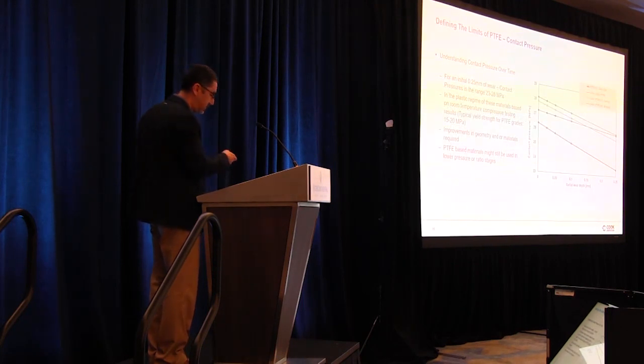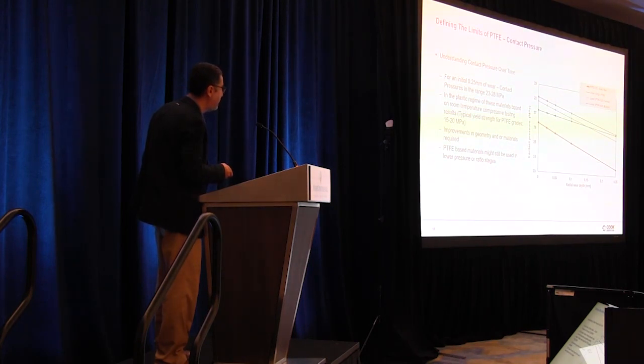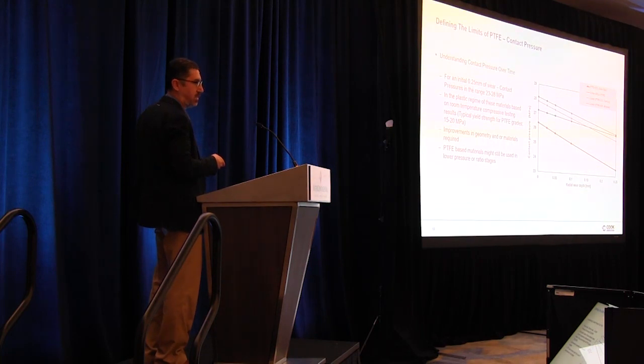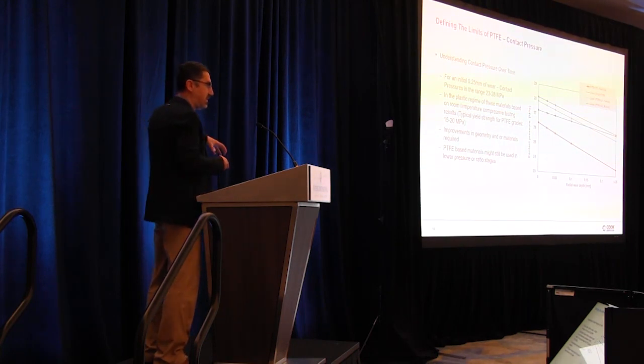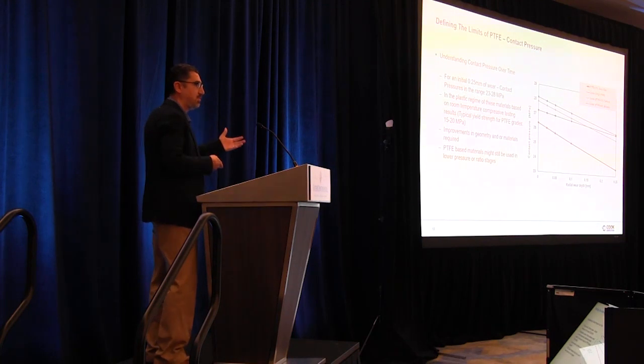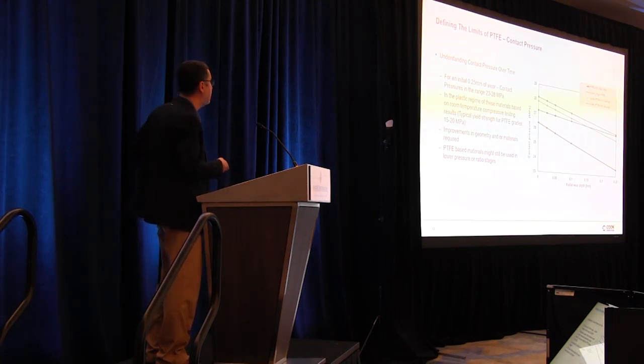When we plug all the numbers in the model, we get the contact pressure estimates for 4 different grades of PTFE. These are some of the numbers we get with respect to different wear levels on the ring itself. Just very quickly, if you look at 0.25 millimeters of radial wear on the ring, we are averaging around 23 to 28 megapascals of contact pressure. So what does this mean? The typical yield strength for a PTFE grade, when you run a compressive strength test at room temperature, is 15 to 20 megapascals. So this is way higher than that level. That means when you apply this much contact pressure, the material will eventually fail and have some plastic deformation and eventually lose the sealing efficiency and fail in the process.